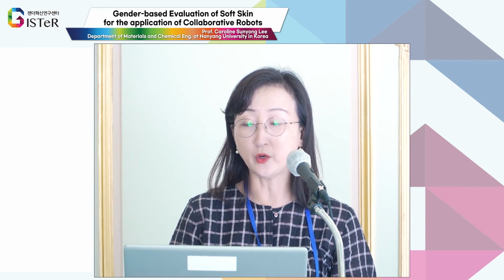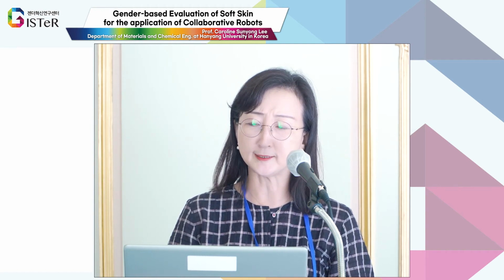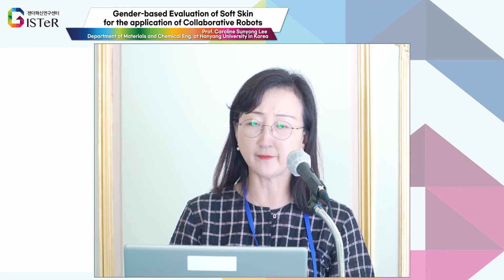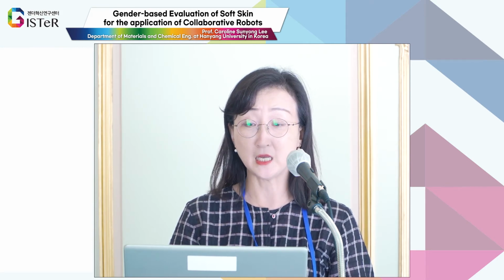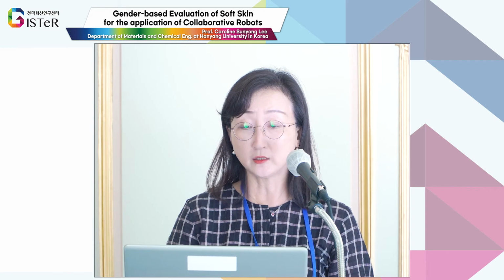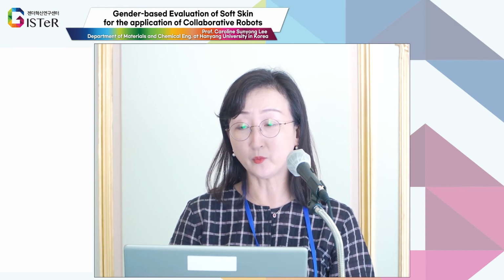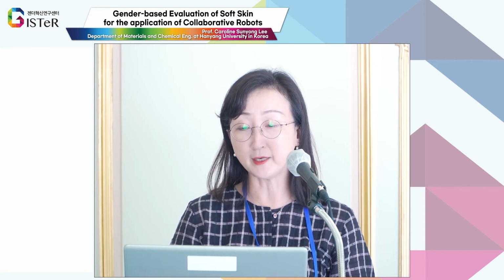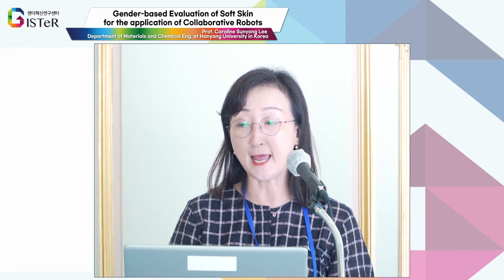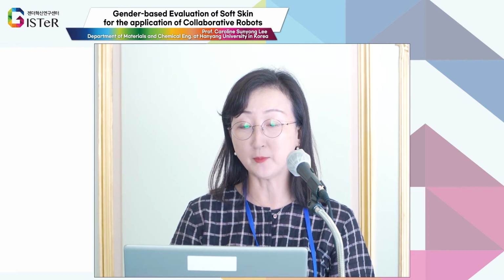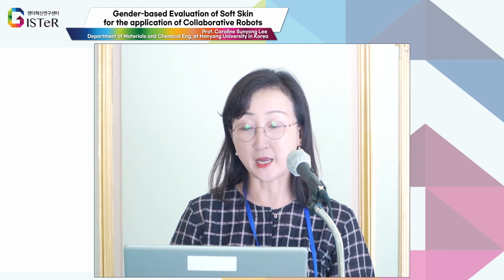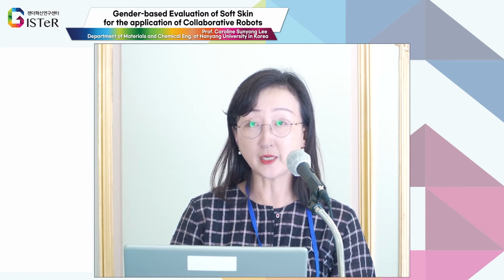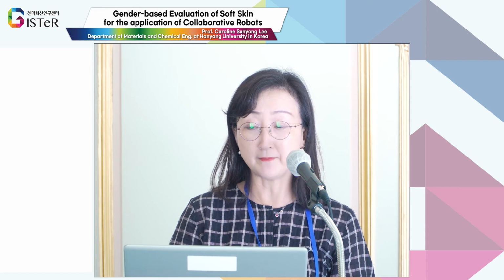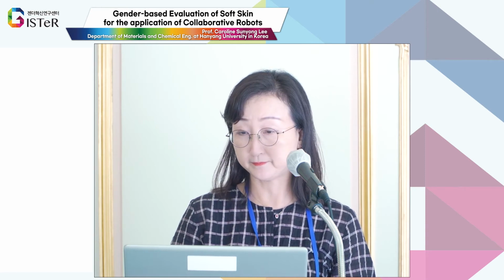And in order to relate stiffness to scientific values, we have conducted a compressive creep test. As you can see here, the compressive creep test is an experiment where the specific sample is pressed under a constant force and then released, to measure how much each sample recovers after the deformation in a given time. Therefore, the larger the strain, the softer the sample it gets. That means it's decreasing stiffness.